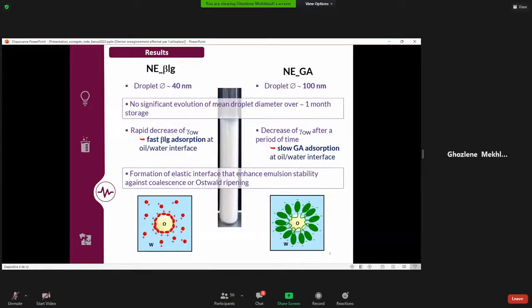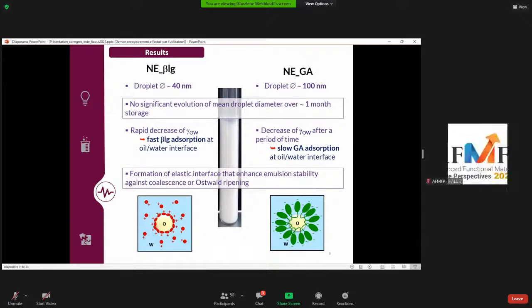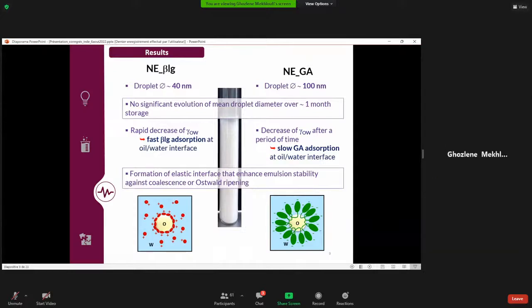Moreover, nanoemulsion stabilized by this protein and the acacia gum showed a great stability owing to the formation of a viscoelastic film surrounding the nanodroplets, thanks to the adsorption of both biopolymers at the interface. And so we obtained emulsions stable against coalescence or Ostwald ripening.